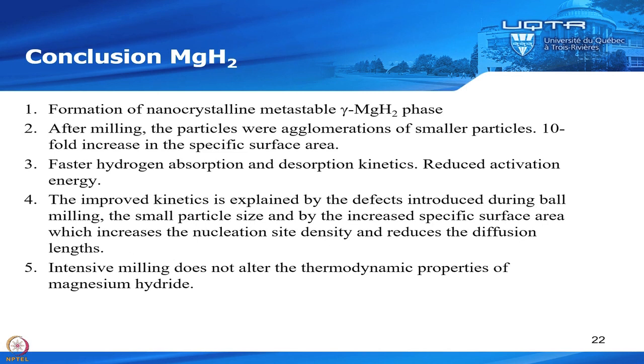So the conclusion for the magnesium hydride: by ball milling, we found that you could have nanocrystalline material with a metastable phase. And after ball milling, the particles were still of the order of micron, but much smaller than before milling. And you have a tenfold increase in the specific surface area. You have a faster hydrogenation and dehydrogenation, and a reduction of the activation energy. So this improved the kinetics, and also because we have defects, and the small particle size and the increase of specific surface area. So these are all features that will make your kinetics faster. Okay, so reduction of activation energy, smaller size, defects, and so on.